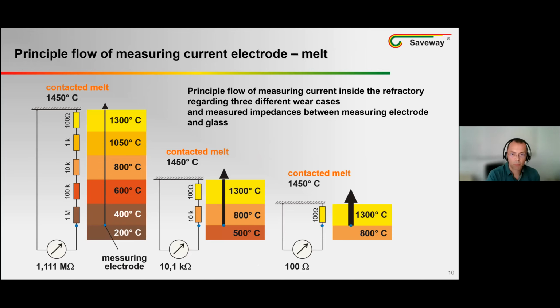Because the higher the temperature of the lining above the electrode, the lower the resistance, and the current will always follow the path of least resistivity. The thinner the remaining lining, the higher the temperature of the refractory material above. So it means that the detected resistance is smaller, as the cases shown here demonstrate. According to this principle, we can monitor the remaining thickness of the furnace lining in real time.